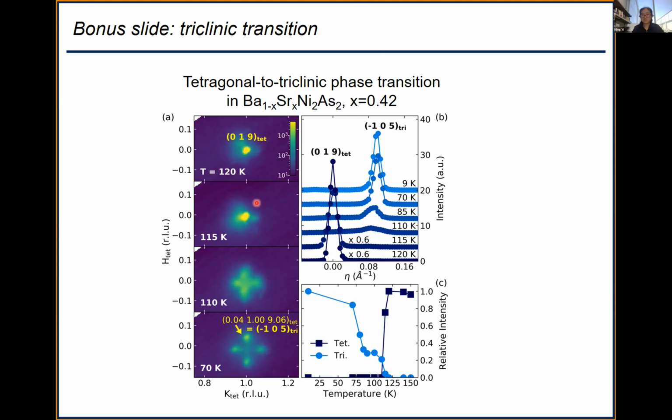Okay, thank you. Maybe then I'll let Christoph ask the first question. I was sort of going in the same direction. Actually, from the diffraction data in Karlsruhe, we also don't have evidence for the orthorhombic phase, but we do have evidence from the high-resolution thermal expansion, which is much more sensitive than the X-ray diffraction. So I think there's very clear evidence for an orthorhombic phase, and this naturally would explain your hysteresis in this phase. You have domains.